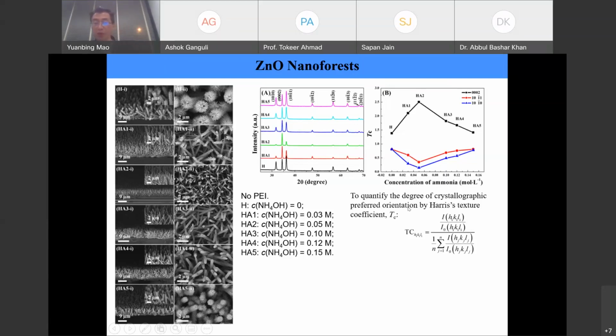So for those of you working with crystals, there is the Harris texture coefficient, TC. This is the equation for how it works. We know these peaks have different orientations, and we use this formula to do the calculations. This I and this I-naught are basically the peak intensities, right? And N depends on how many peaks we use in the calculations. Based on this figure, you can see that we picked these 3 peaks, so N equals 3 here. One thing I want to show you quickly is that the 002 peak's intensity initially increased, and then after passing this point, it decreases, while the other 2 peaks have the opposite trend.